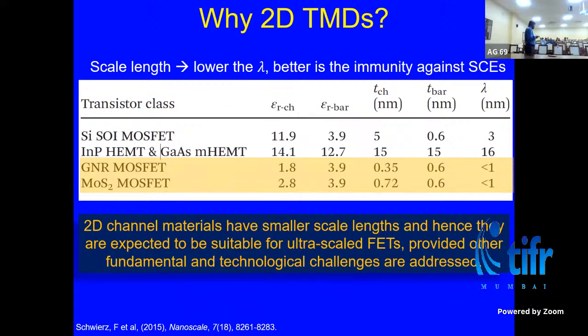One more thing to add here is that graphene not having a band gap basically limits its application in switching applications like CMOS. But graphene would be interesting for, say, RF applications, or applications where you don't have to turn off the transistor, where it's fine to have the transistors on and you're just modulating the conductivity. For example, compare how much you can scale a silicon MOSFET versus a MoS2 MOSFET or a TMD-based MOSFET. For a given channel thickness, you can go down to about a 5 nanometer limit in the case of silicon, whereas if it is TMD, you can go down to about a 7 angstrom limit.